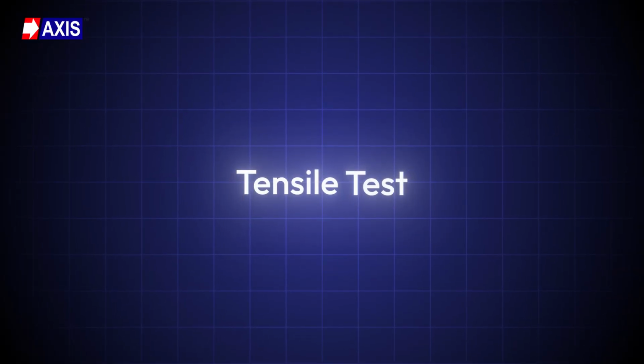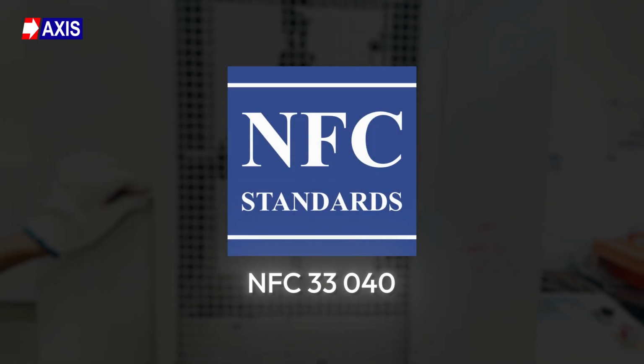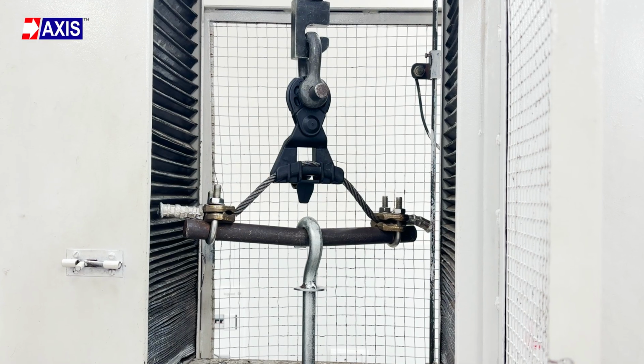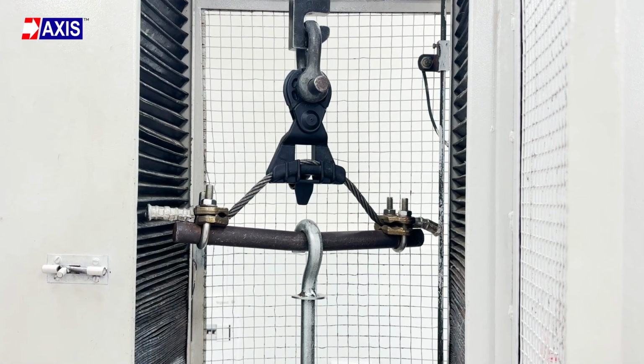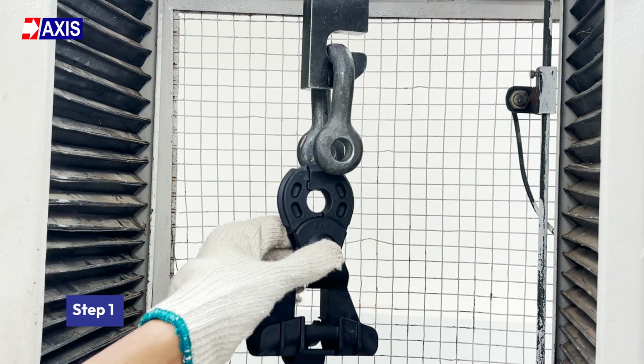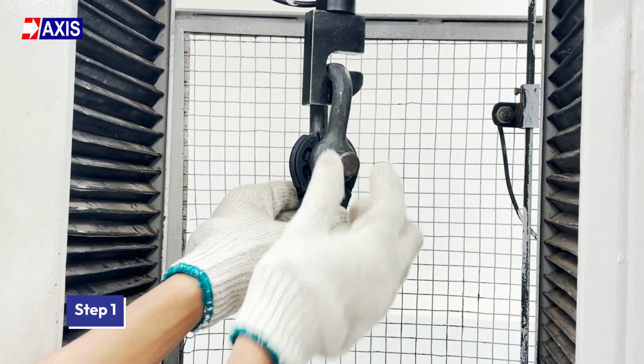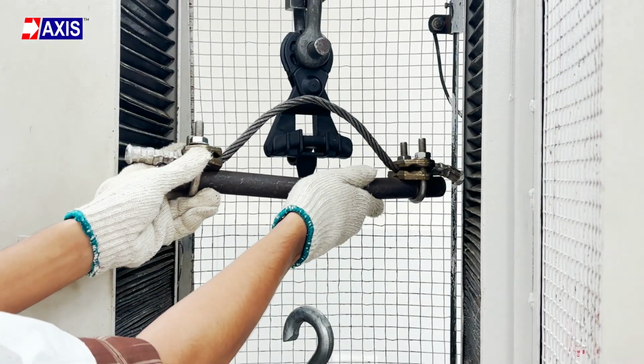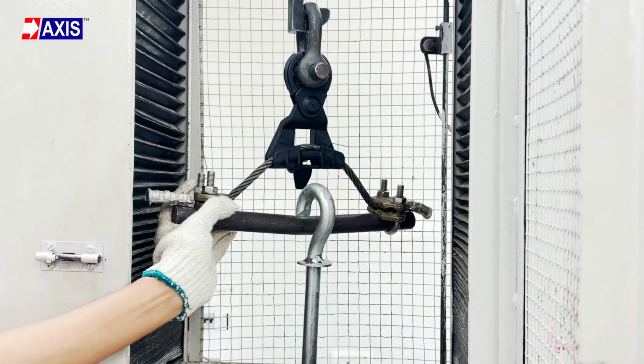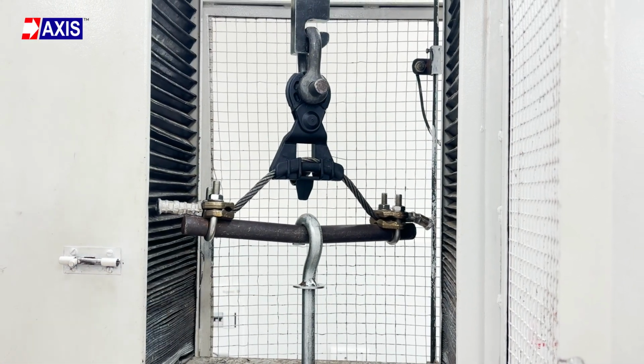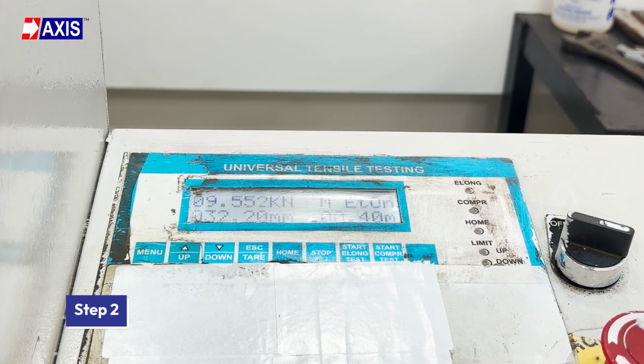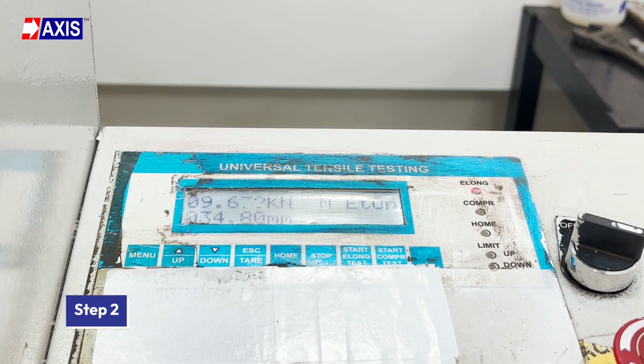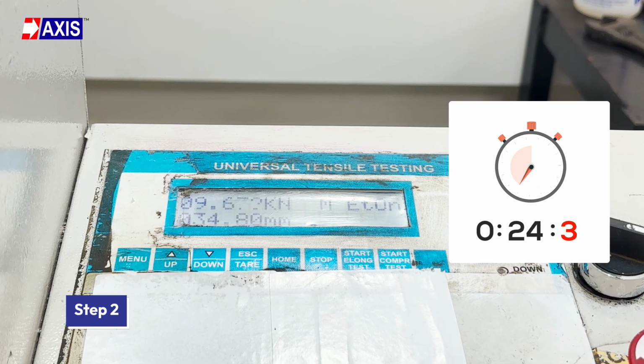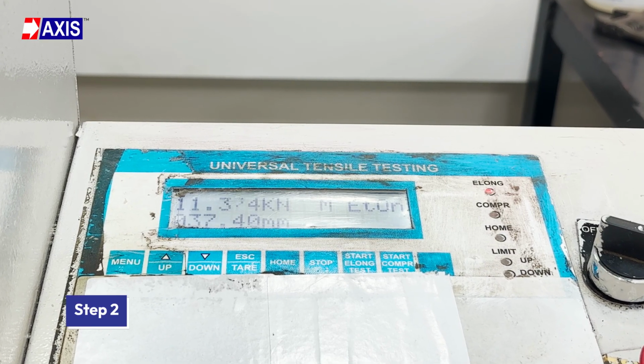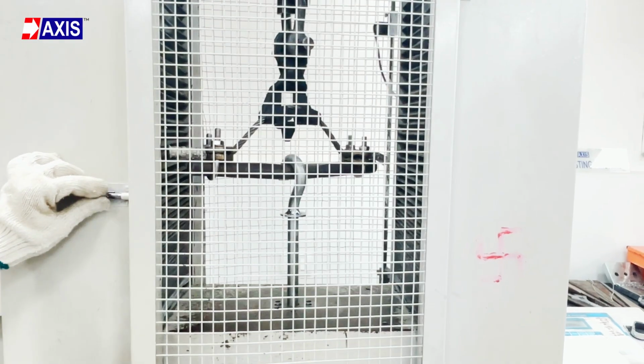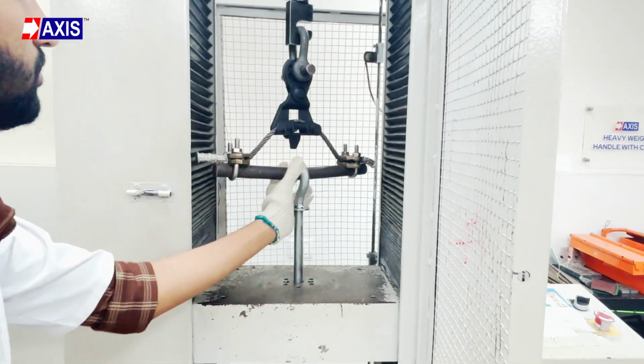Lastly, tensile test as per NF C 33040. This test checks the mechanical strength of your suspension clamp under full tension. Step 1. Mount the clamp in the tensile testing machine with the load aligned to the clamp fixture. Tighten the grips and ensure it is securely held in the fixture. Step 2. Apply the load gradually up to 9.6 kN. Hold for 1 minute and then take it up to 12 kN. The clamp passes the test if there is no visible deformation, cracking, or fracture.